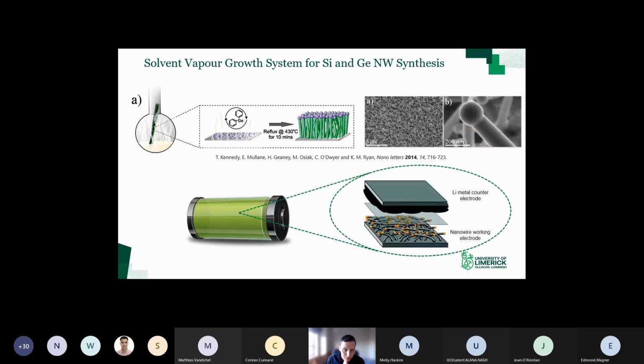So what we did then is we took that material and used it as the working electrode in a Swagelok type cell is what we use. So a Swagelok type cell is a very basic test cell that we can assemble quite easily in the lab. So what we had was a 2 electrode setup. On one side, we had the nanowires grown directly from the current collector. Then a separator soaked in a carbonate-based electrolyte, and then the counter electrode was lithium metal.